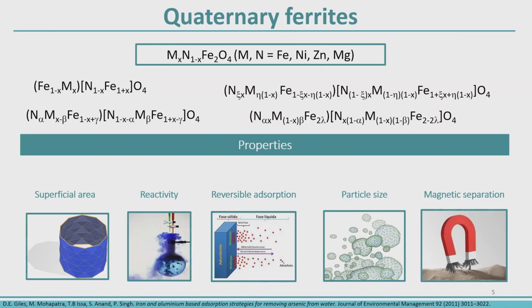But when these two cations are distributed between tetrahedral and octahedral, we have found these three proposed formulas. We propose this one here, but we have found in the literature other formulas that are equivalent. We can demonstrate that all formulas are equivalent. But you can notice that M and N cations are distributed on both sides, tetrahedral and octahedral. So the question here is how can we determine the distribution of the cations in these two sites, because this is important for the properties.